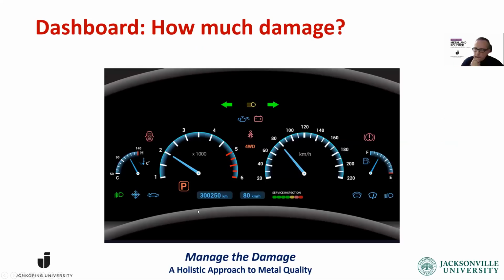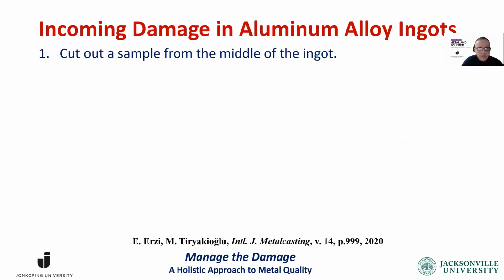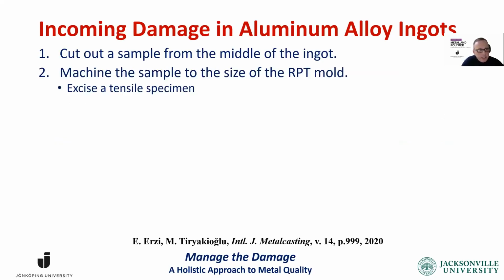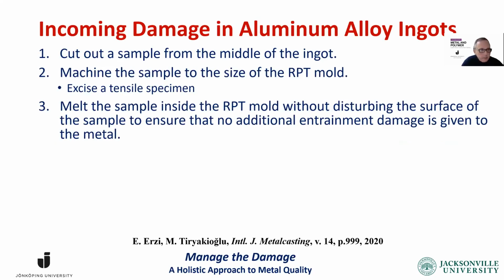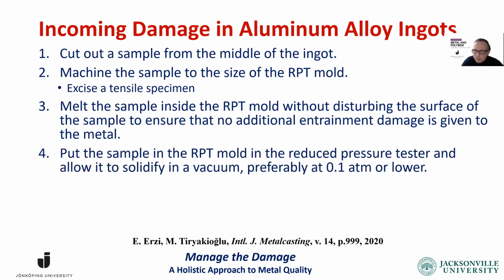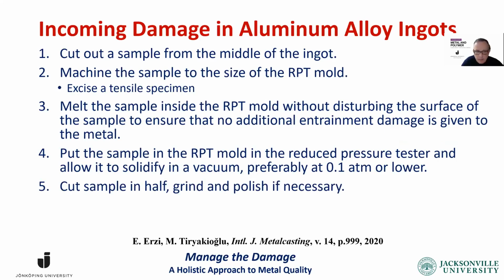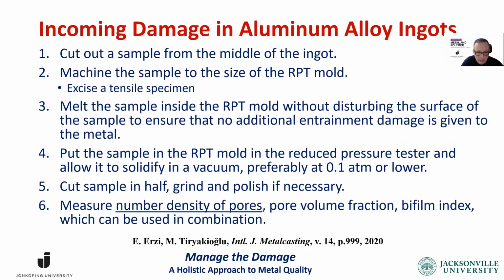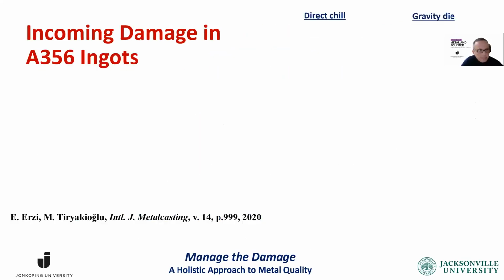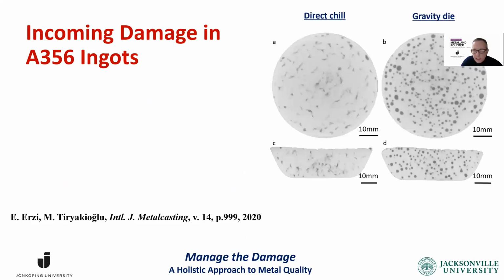So I'm proposing that you have a dashboard of how much damage you have. So for the incoming damage, you can cut a sample from the ingot, machine the sample and melt it, and put it in the RPT mold and cut it in half, grind and polish, and then the number density of pores will tell you how much damage there is. So we have a case study here. We have the direct chill ingot and gravity die.